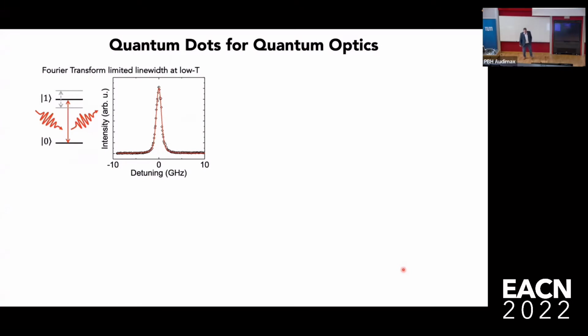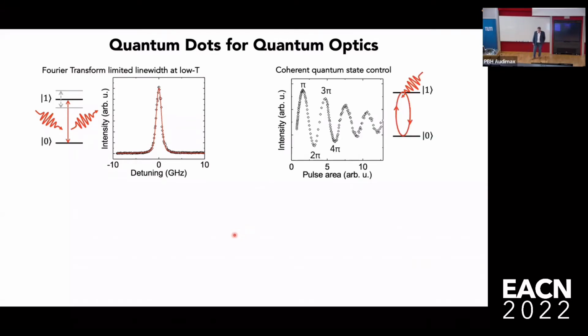So what kind of properties do they have? Well, they have what are clearly Fourier transform limited transitions. This is a resonance fluorescence spectrum obtained by tuning a single frequency laser across the transition. The line width these days, at low temperatures, is Fourier limited. You can apply pulses of light, and if you apply pulses of light, you see what at first glance looks like classic 2-level systems interacting with light, so coherent control, Rabi oscillations. And of course, you can come with a pi pulse, and by doing that, drive the system and coherently prepare the upper level to allow it then to decay and emit a photon.